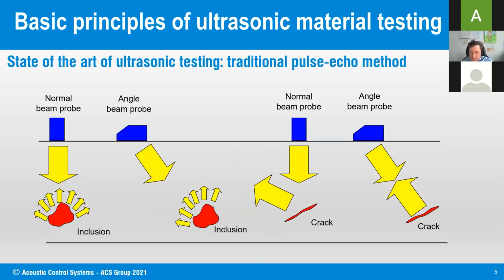Obviously this approach is not perfect, because the reflectivity of the defect may depend not only on the size of the defect, but also on the type of the defect. Volumetric defects reflect in all directions, while flat defects like cracks have a certain beam directivity, so that not every transducer is capable of catching them.